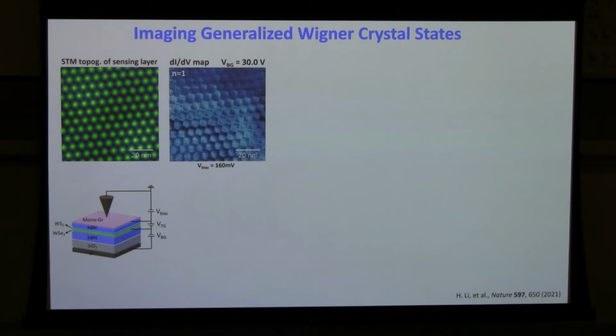We took what we call a dI/dV map, and the electronic structure of this graphene top layer is here. This is what we measured. Now what you're seeing here is all these white blobs, and each of these white blobs represents a single electron underneath. So that white blob is the effect that the electron underneath has on the electronic structure of the graphene. So this periodic pattern represents a periodic pattern of the electrons underneath in the moire heterobilayer.